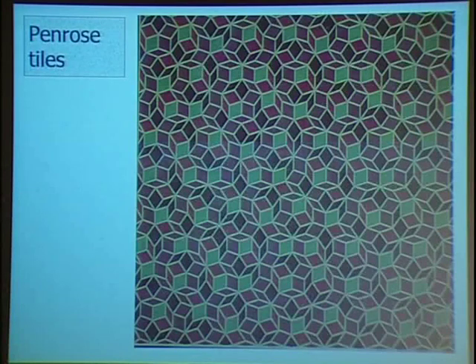Now, another scientist named Alan Mackay, also living in our time, he's also British. He took Penrose tiles, put them on a slide, and put a laser beam through them, and lo and behold, sharp diffraction spots appear. Of course, nowadays you do it on the computer within a fraction of a second, from the image to the Fourier transform diffraction pattern. You do it on the computer, it's called FFT, fast Fourier transform. But he did it as we did it before with the laser beam. And he found that Penrose tiles will give sharp diffraction spots in the reciprocal space. This is not trivial because it's not periodic.